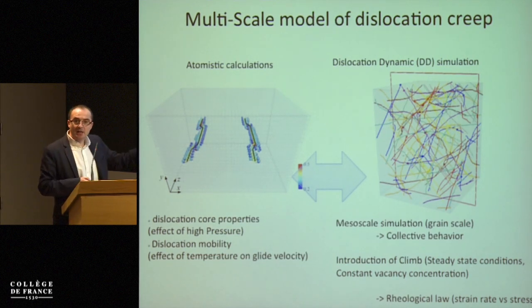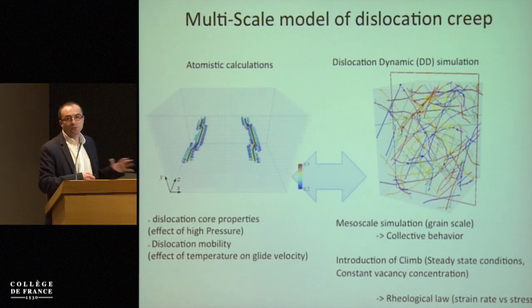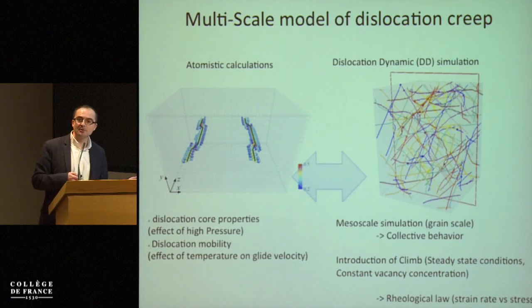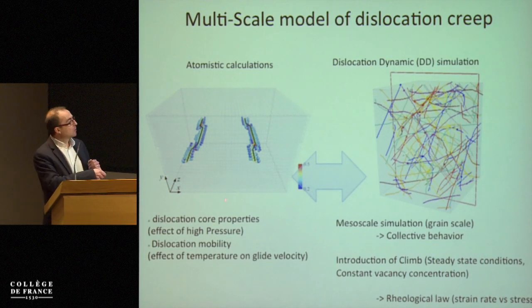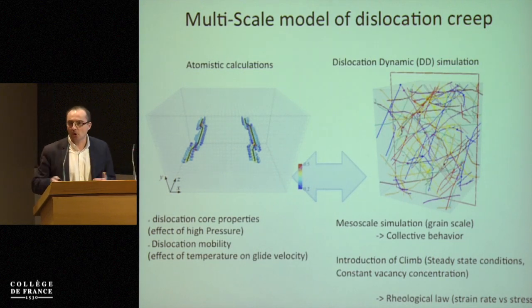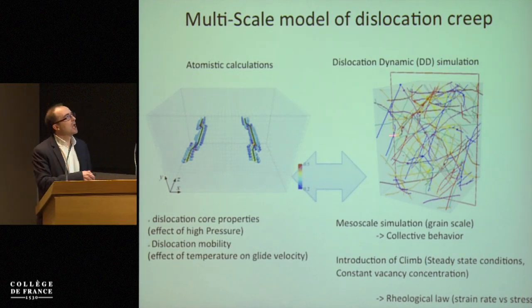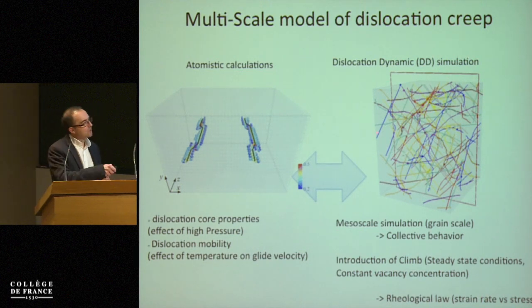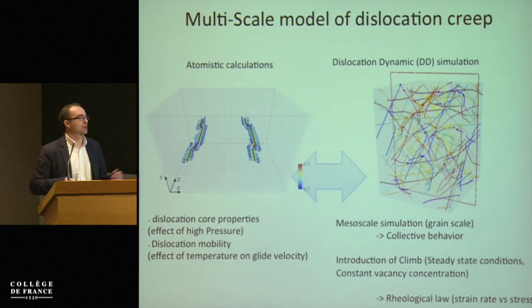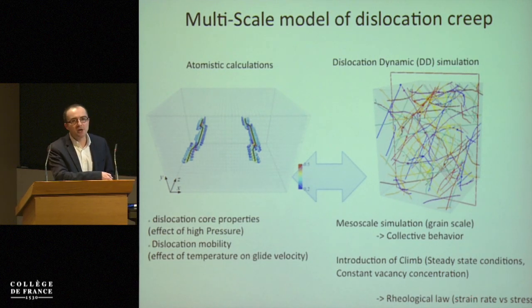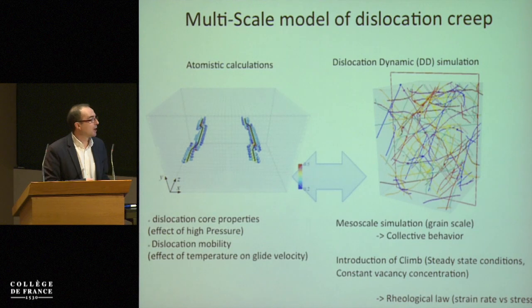At the atomistic scale, we look for intrinsic properties of the dislocation: dislocation mobility, effect of pressure on this mobility, and effect of temperature on this mobility. Once we have these intrinsic properties, we transfer them to a mesoscale simulation that treats the collective behavior of all defects present in the crystal — this is done using dislocation dynamics (DD) simulation. At this stage we also introduce dislocation climb. The goal is to ultimately say something about strain rate versus stress and constitutive rheological laws.